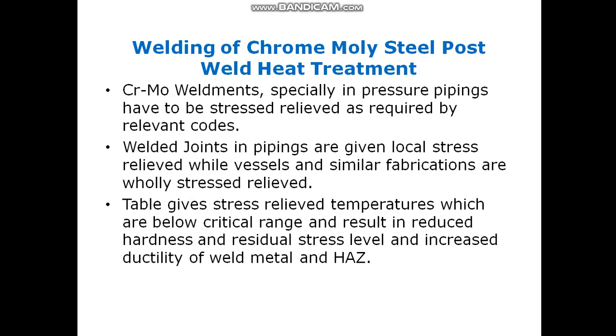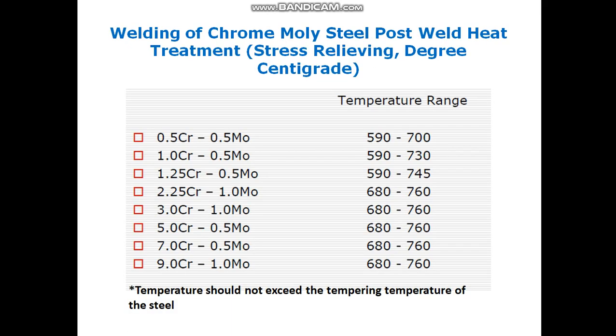In the next slide, there will be a table that gives some recommendations on the stress relieving temperature, and that must be below the critical range. It means it must be below the lower critical temperature, and that should result in reduced hardness and residual stress levels, and at the same time should increase the ductility of weld metal and heat affected zone. So here are some recommendations on the stress relieving temperature in degrees centigrade for materials from half chrome half moly to 9 chrome 1 moly steel. The temperature ranges are mentioned here, but it must be understood that this temperature should not exceed the tempering temperature of the steel.